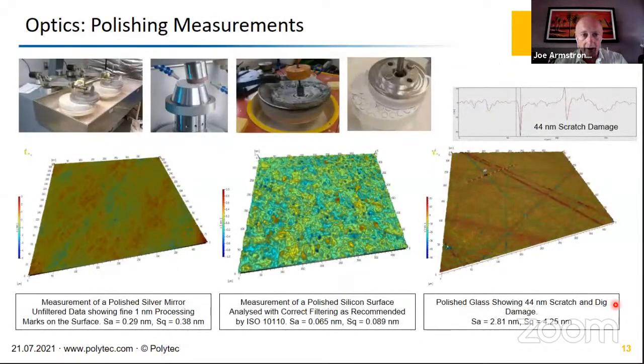Of course, here I'm talking about optical polishing, giving some examples of different sorts of fine measurement surfaces. So I have a polished silver mirror surface. You can see the average roughness is 0.29 nanometers. If you apply some filtering, so you want to conform with a standard such as ISO 10110, then you can see you can get down to 0.065 nanometers, which is pretty incredible. And at the same time, you can look at scratch and dig errors as well.